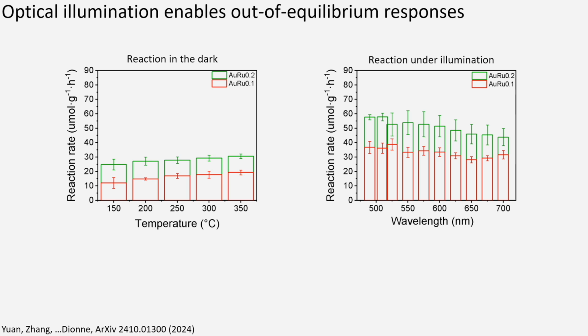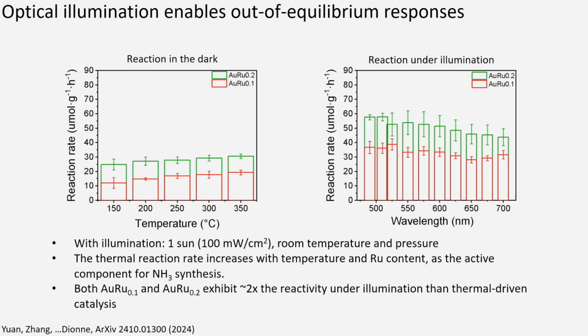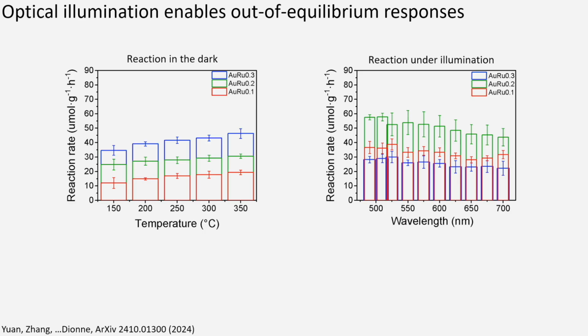Similarly, here, under illumination, as you increase the number of active sites, that reaction rate also goes up quite substantially. But now, if we go up to 30% ruthenium, you'll notice that the reaction rate actually goes down for photocatalysis, up for thermocatalysis. So this means there's kind of a Goldilocks effect where when you're doing photocatalysis, you want to have a strong enough optical absorption. And in this case, the ruthenium kind of quenches the optical absorption.